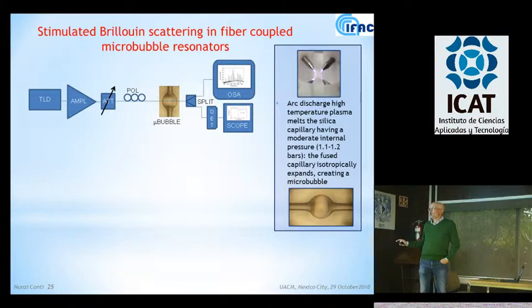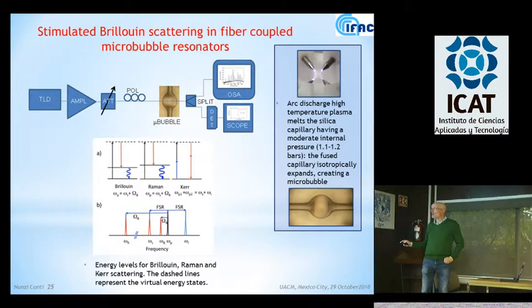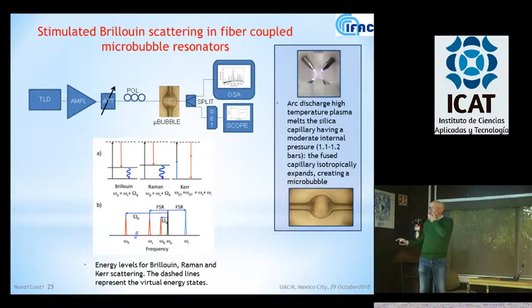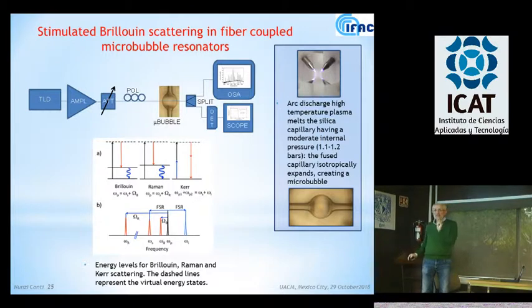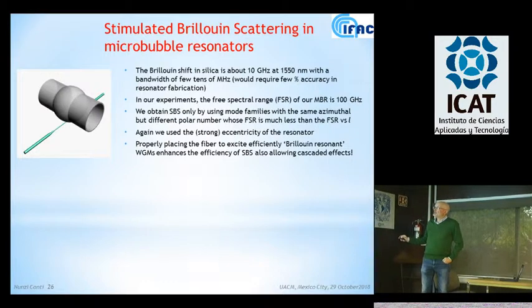Another example of how important the way you couple light is, for instance, generating stimulated Brillouin scattering in a microbubble resonator. Here is the scheme of this non-parametric nonlinear effect. And what we know is that in silica, the Brillouin level is about 10 gigahertz apart from the pump, but it's a very narrow gain bandwidth, which translates into the fact that you would need an extreme precision in making your resonator, which is not possible. And so how did we demonstrate this stimulated, actually cascaded, Brillouin scattering?